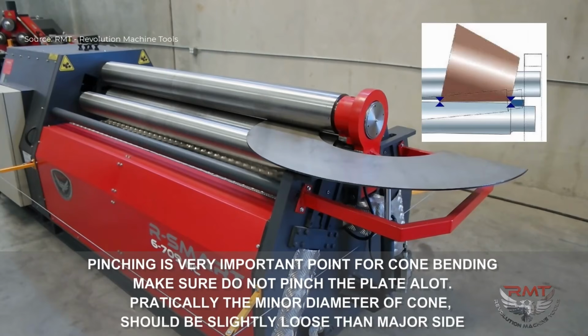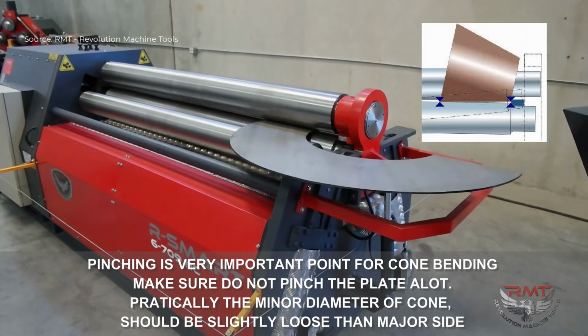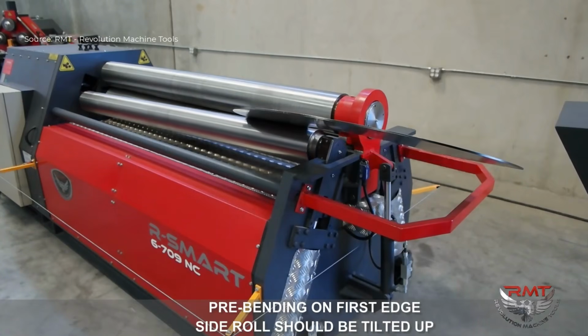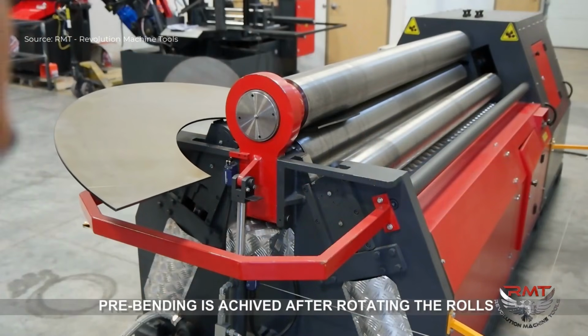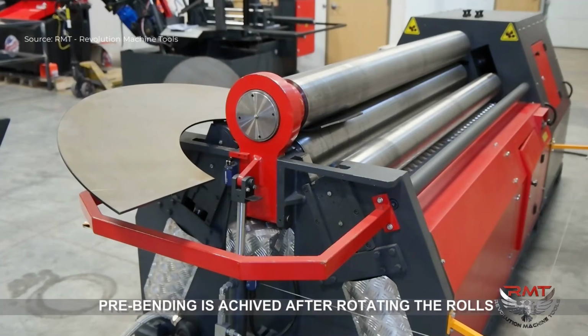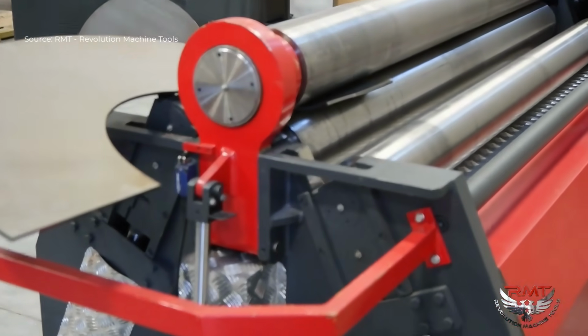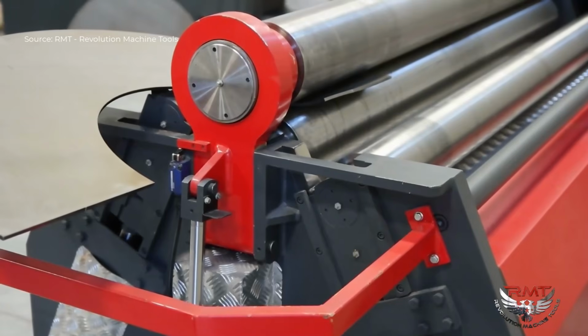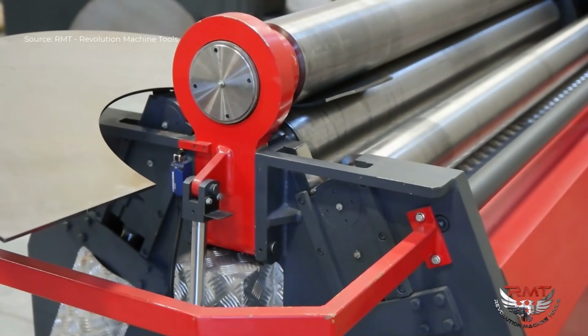The steel plate is first positioned in the 4-roll plate rolling machine, where the top roll and the 2 side rolls grip it while the bottom roll provides the driving force. At this stage, pinching is a very important point for cone bending. The operator must make sure not to pinch the plate too tightly. Practically, the minor diameter side of the cone should remain slightly looser than the major side, because this difference in grip allows the material to flow into a conical shape rather than a simple cylinder.